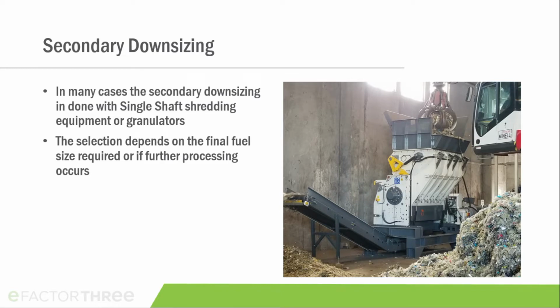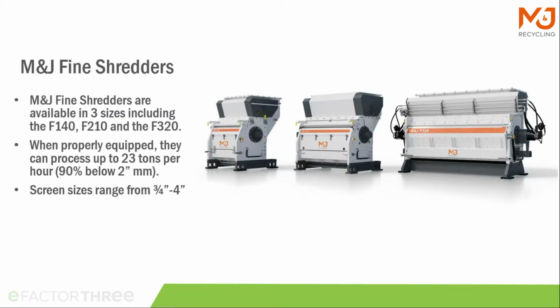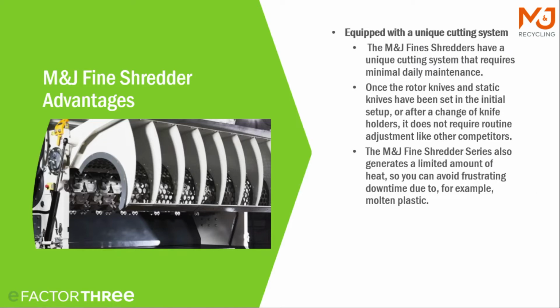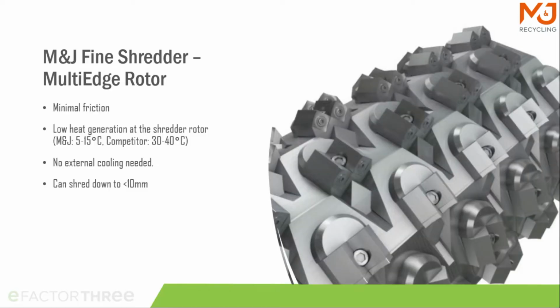And then the secondary downsizing is typically done with single shaft shredders, in some cases granulators. The selection really depends on the material that you want to process. So we offer fine shredders in different sizes that go up to 23 tons an hour. A lot of single shaft shredders use the same principle, small square inserts on a rotor. In certain materials, this design with a multi-edge rotor gives us some benefit, so that we don't get melt of specific LDPE films.